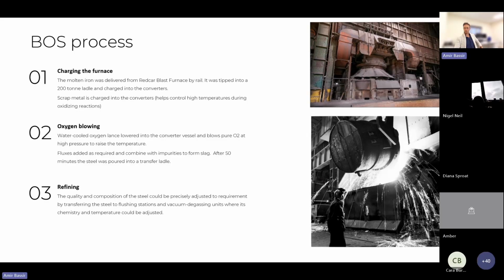Then we've got oxygen blowing. Water-cooled oxygen lances are lowered into the vessel and blow pure oxygen at very high pressure, which raises the temperature of the iron and initiates exothermic reactions and oxidizes the impurities. During this process, various fluxes are added, which combine with the impurities to form slag, which can be removed. After about 50 minutes, the furnace is tilted and the molten steel is poured into a ladle.